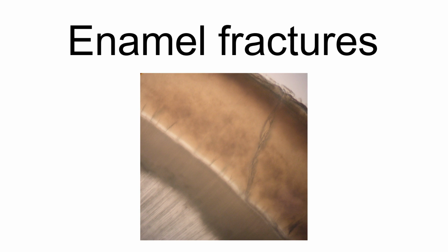Some sources consider them to be of no clinical significance. However, they have been noted to be an important potential source of enamel fractures that arise after extended use or overloading. It appears that, although enamel easily starts to form the fracture defects of enamel tufts, they then enable enamel to resist the further progress of these fractures, ultimately preventing mechanical failure. This fracture resistance is why tooth enamel is 3 times stronger than its constituent hydroxyapatite crystallites that make up its enamel rods. Enamel tufts do not normally lead to enamel failure, due to these defects stabilizing potential fractures.